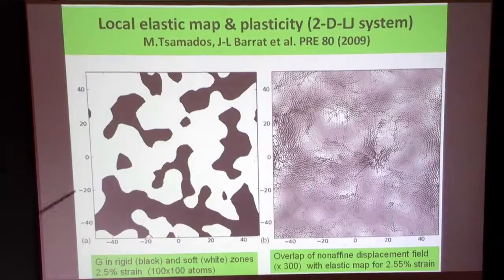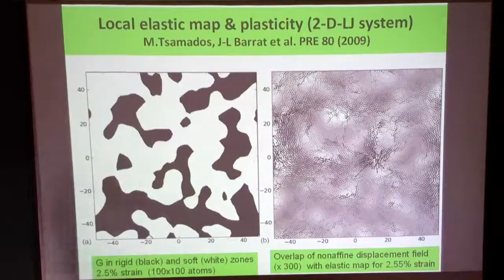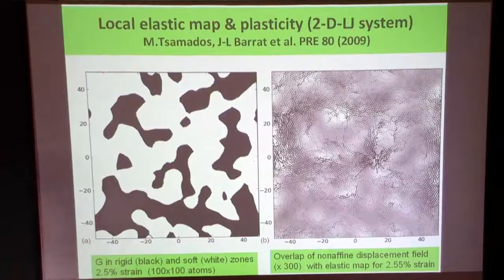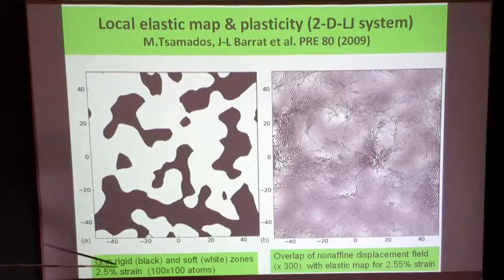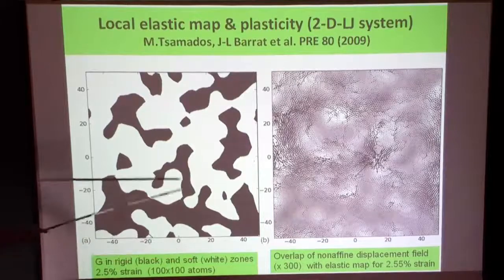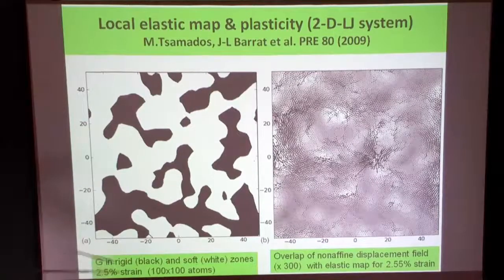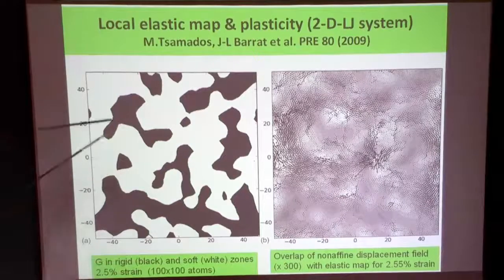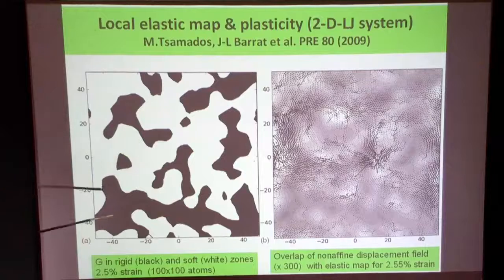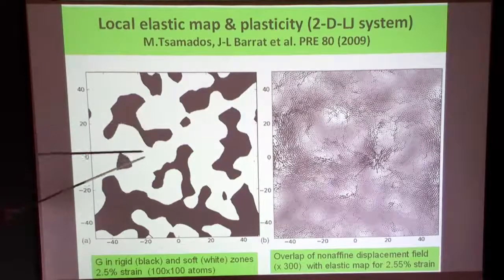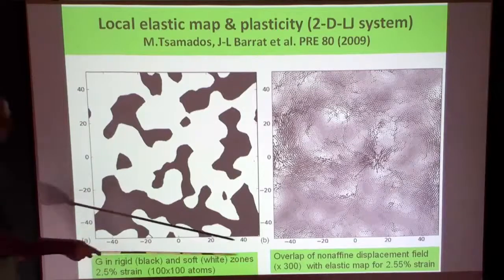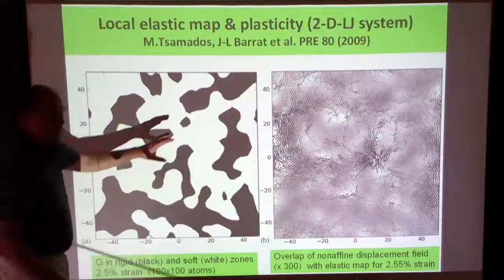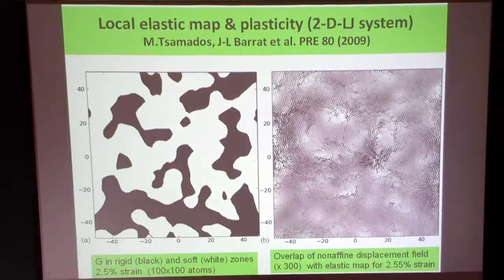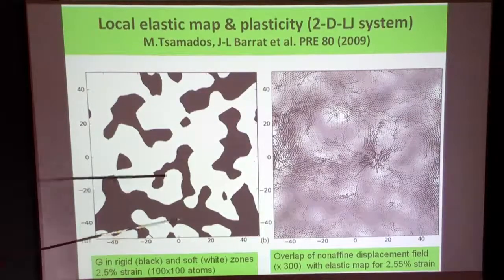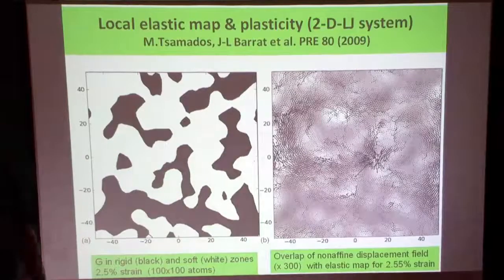Jean-Louis is still here, so he has worked out prior to our work actually a 2D Lennard-Jones system MD simulation in 2009, and showed that there is the modulus, rigid, which he calls black, and soft, white zones, also divided under strain. And this is 100 by 100 atoms, much different scale, but you see there is some inhomogeneity which nobody doubts in the meantime. And you see that is soft and rigid areas, and you overlap then in nonaffine displacement field. Obviously, where it starts, everything is in the soft spots, the soft modes, we call later on in the K-space discussion. And that's obviously the case where the motion starts, where the modulus is soft, or I will show it to you later on, even negative.